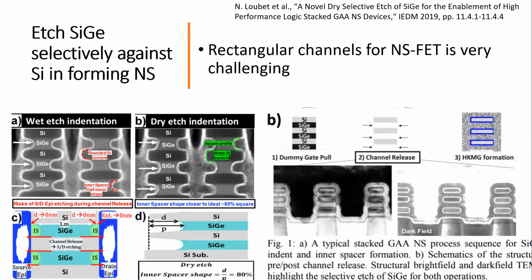So they calculated this selectivity. Okay, it can be very high. And here, but it still has a little bit. You see that? It's still, to some extent, a rounded shape. It's just better than the wet etch. That one is very round. And at the same time, you can see that the silicon is a little bit lost. You have a silicon loss. And that is not good either.